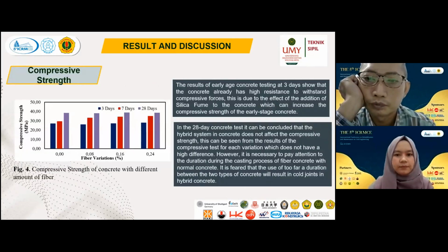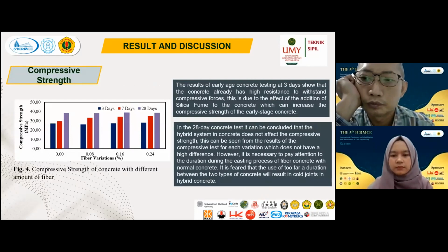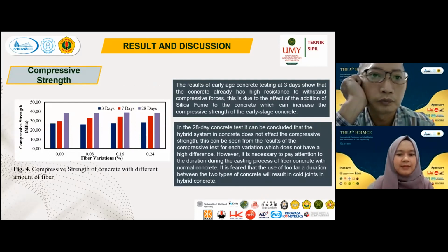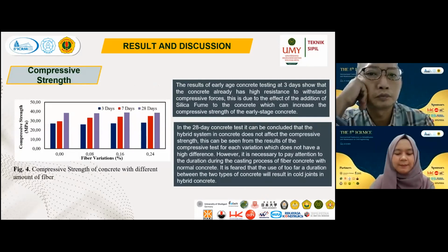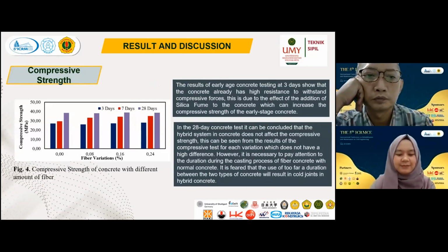This is the result for compressive strength. In figure 4, we can see the compressive strength of concrete with different amounts of fiber. The result of early age concrete testing at 3 days shows that the concrete already has high resistance to withstand compressive forces. This is due to the effect of the addition of silica fume to the concrete, which can increase the compressive strength of the early stage concrete.